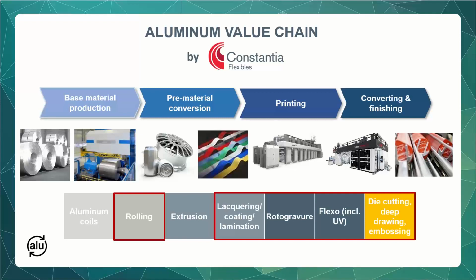Thank you, Thomas. In the further course of this webinar, you will learn more about our foil-based sustainable packaging solutions. But before this, I want to explain our aluminium value chain, or our vertical integration for producing foil packaging. We start basically with our rolling mill, and in our rolling mills, the aluminium foil stock is rolled down from a thickness of normally about 600 micron to thinner gauges. The current minimum is about 5.5 micron.